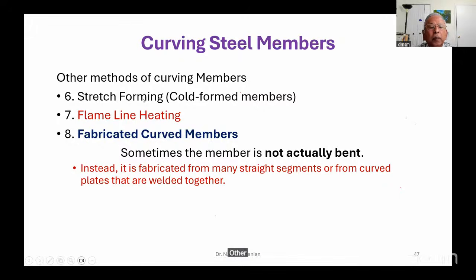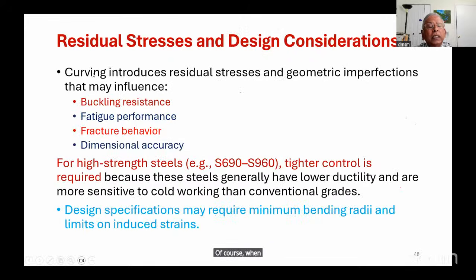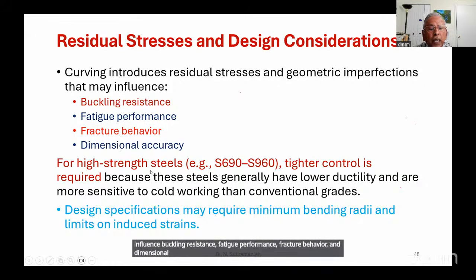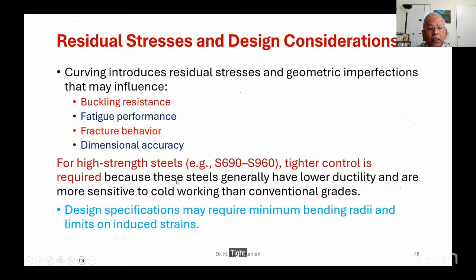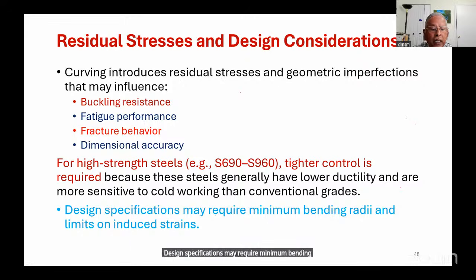Other methods of curving members are stretch forming, which is used for cold-formed members, and flame line heating. Sometimes the member is not actually bent. Instead, it is fabricated from many straight segments or from curved plates that are welded together. Of course, when you are bending like that, and using heat, it produces residual stresses and geometric imperfections. It may influence buckling resistance, fatigue performance, fracture behavior, and dimensional accuracy. For high-strength steel, tighter control is required because these steels generally have lower ductility and are more sensitive to cold working than conventional grades. Design specifications may require minimum bending radii and limits on induced strains.